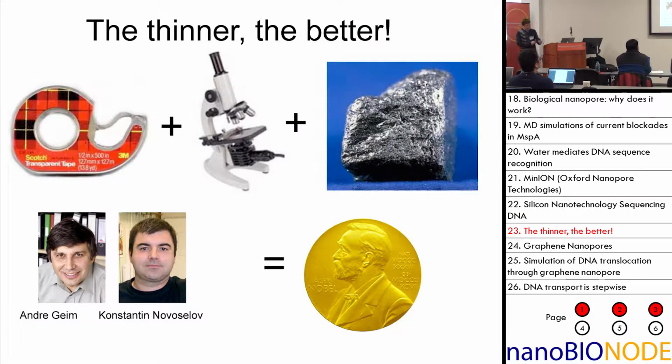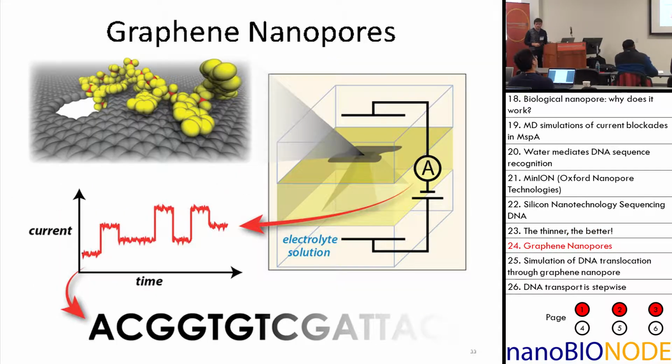Yeah. Well, obviously, the problem with silicon nanotechnology was that, however thin they were, you still end up with those polysilicon layers that are tens of nanometers in size. So really, another key development was the advent of graphene, right? Graphene was thought to be an ideal material for building a device for DNA sequencing because it's so thin. Ideally, with a graphene layer, which is just one carbon in thickness, you should be able to isolate individual nucleotides. And maybe that's the way forward, right?